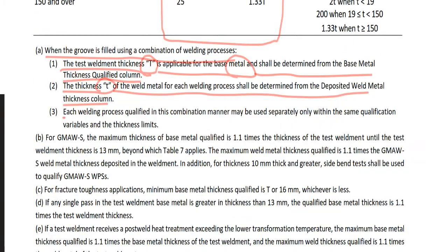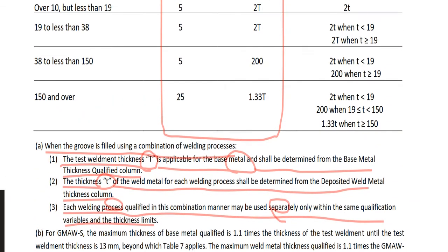And number three, each welding process qualified in this combination manner may be used separately only within the same qualification variables and thickness limits. Separate process. So if you use GTAW and SMAW, the thickness qualification should be applied separately. So for example, we have a groove weld here, and you weld it with GTAW, root pass, and second pass.